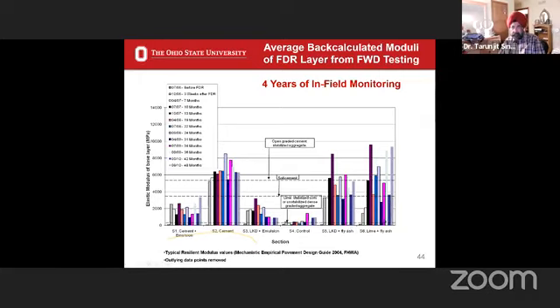And this line that you see here goes up till here. I don't know if you can see that. This line goes here, and this one is going up till here. So our conclusion is this. I've already talked about the control. The LKD emulsion and cement and emulsion ones we believe did not work for us. We probably didn't have the right emulsion. But the cement one obviously exceeded that of an open graded cement stabilized aggregate.